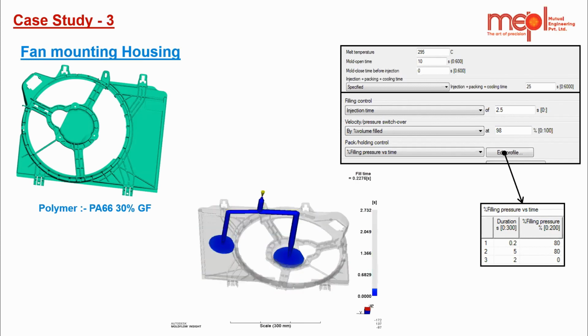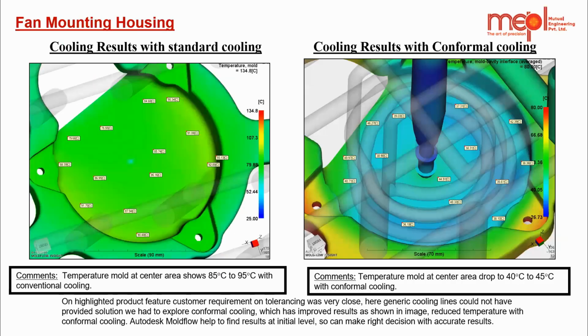If you can see, the center area of the part was very critical, and to achieve the close tolerance of this part, we have done conformal cooling. As I told you, this is the hub area, which is very challenging because we have a requirement of very close tolerance. With generic cooling, with baffles and lines, we could not achieve the desired mold temperature. As you can see, before, with the standard cooling, the temperature of the area was 85 to 95 degrees Celsius, which is not acceptable.